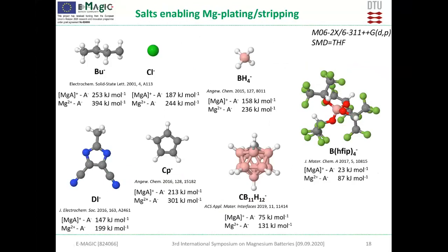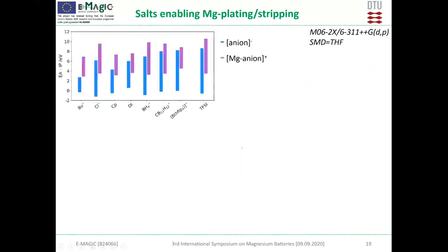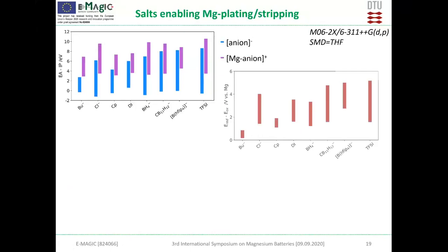First of all, we went through the literature, studying different anion salts that were reported to provide good plating stripping, and calculated the interaction energy for them. We see that for boron ones, the interaction energy is quite small, but for others it can be higher, and it's still possible to plate. So it's not the most important. We also looked at the stability, calculating electron affinity and ionization potential, also for TFSI, which we know really doesn't work, to try to see the difference. We also relaxed the structure and calculated reduction and oxidation potential, but we cannot see anything indicating.